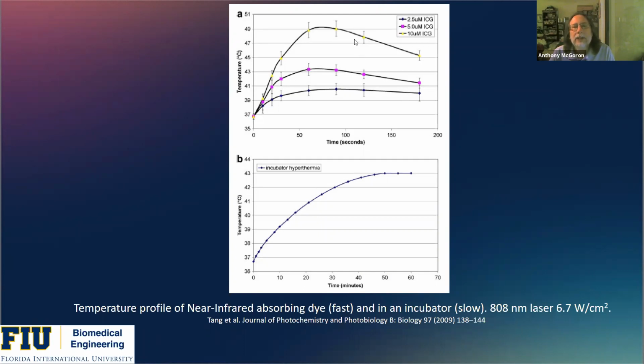So here I show when we expose a 2.5 or 5 or 10 micromolar concentration of indocyanine green to an 808 nanometer laser at 6.7 watts per square centimeter, the ICG will absorb the energy, and part of the released energy is fluorescence, but part of the released energy is heat. And with a 5 micromolar concentration, we can increase the heat to 43 degrees. 43 degrees is what I refer to as a mild hyperthermia. It's not enough to ablate the cells, but it's enough to modify the biology of the cells, and cancer cells respond to this mild hyperthermia at about 43 degrees, whereas normal cells do not. So this 43 degrees is our target for what I call mild hyperthermia.